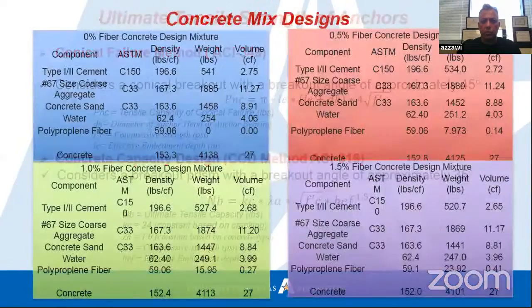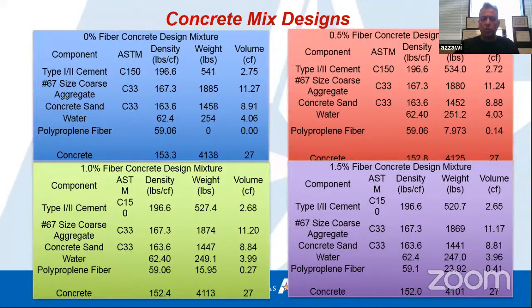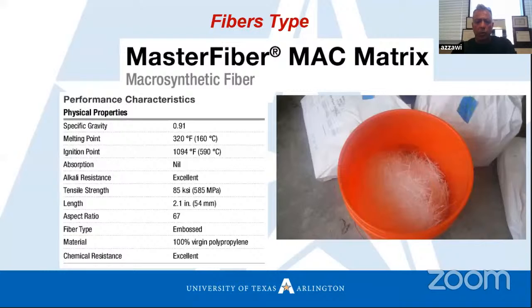That's why we need to find some formulation, some experiments to find the tensile strength of anchors with fibers. Four mixes we prepared at the lab here at the University of Texas. One mix with 0 fiber, the other mix with 0.5% fiber by volume. And as I mentioned, this is polypropylene fiber, synthetic fibers. The third mix is 1%, and the fourth mix is 1.5% fiber. This is the fiber we used. We ordered it from a manufacturer here in the US. We used the master fiber, and these are the properties of the fiber we used.